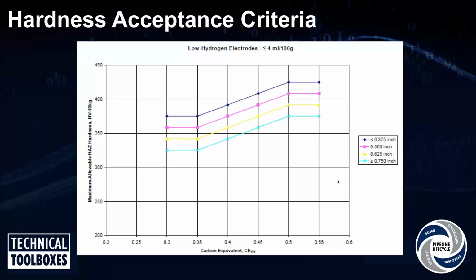Now these different lines on the graph represent different thicknesses of material. And thicknesses are related to tensile stress by the term of restraint. So the thicker the material, the higher the restraint, so the higher tend to be residual stress and risk of cracking. So the thicker the material, the less hardness is acceptable, and then the higher the CE, the higher hardness you have.